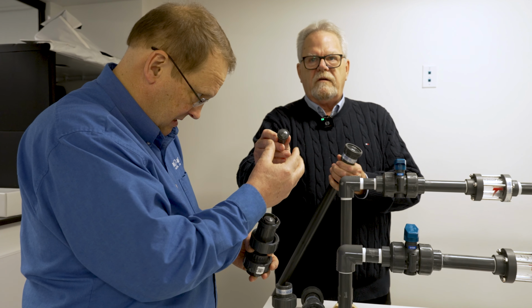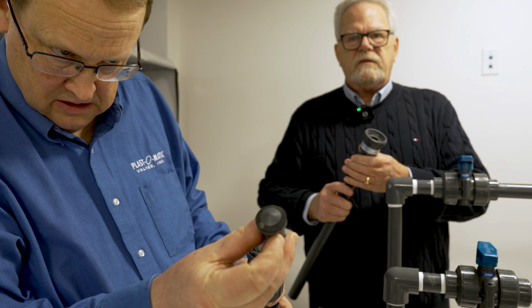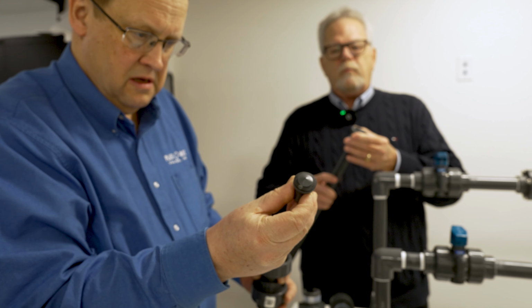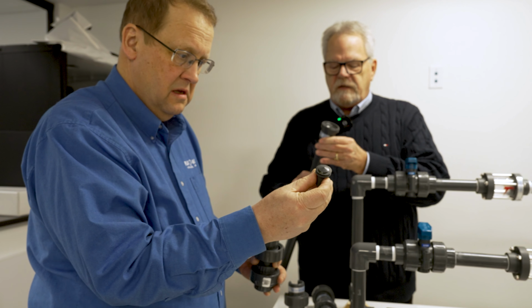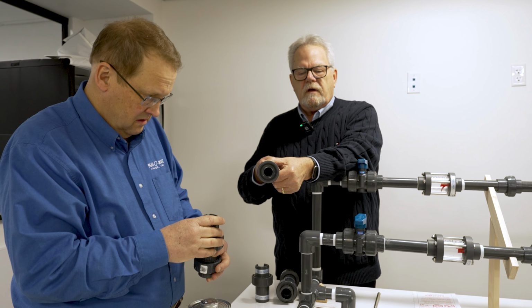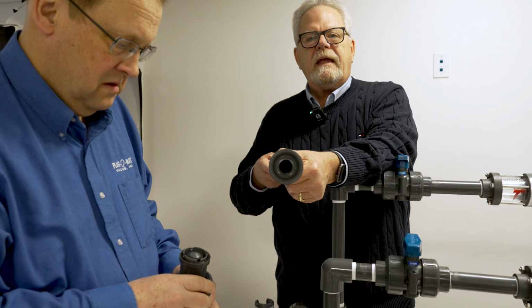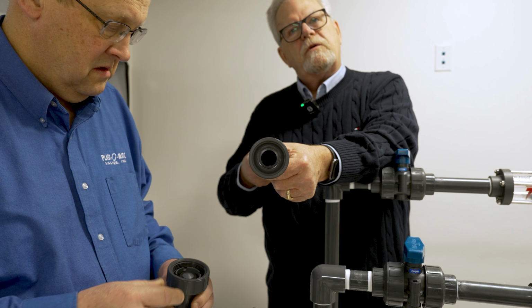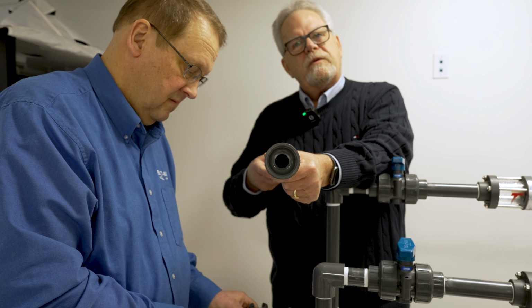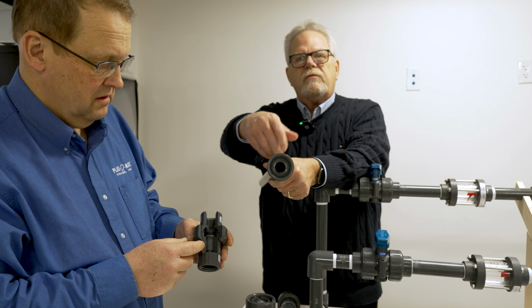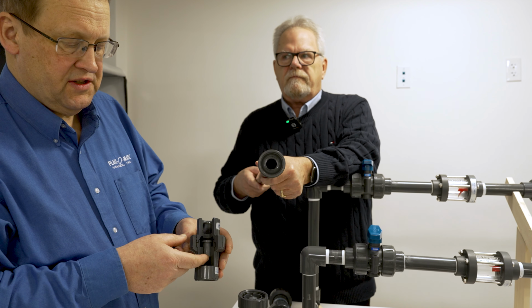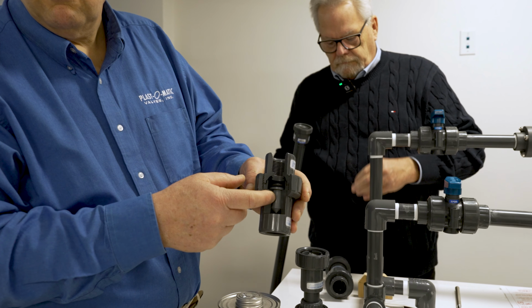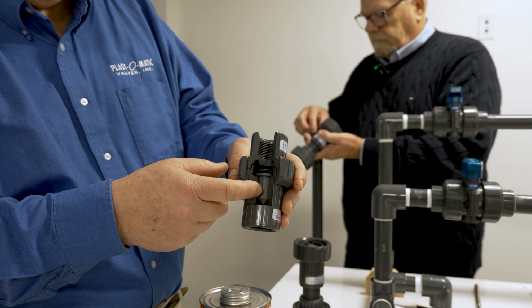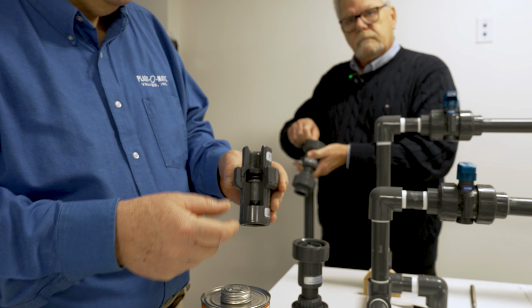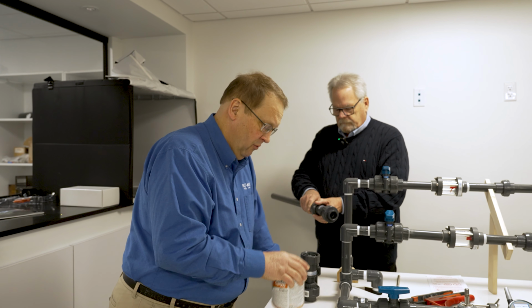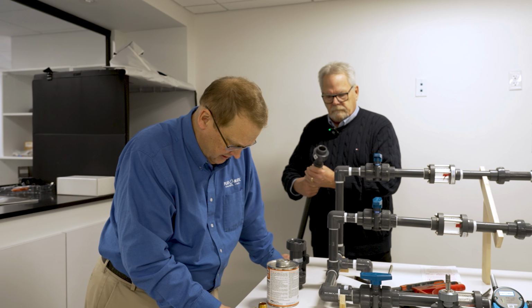Here we see the seat with a little bit of the solvent cement on the seat, and that would harden in the drying process and would then cause the valve to leak. And in addition to that, in this particular instance, there's solvent cement on the ID where the piston rides up and down, and that compromised the piston's ability to move. So when the customer tested this valve, water just rushed right through it, and the valve failed testing. The piston has to move, and in here, they inadvertently cemented this component in place so it wouldn't move at all. So that's a prime example of what can go terribly wrong with solvent cement.